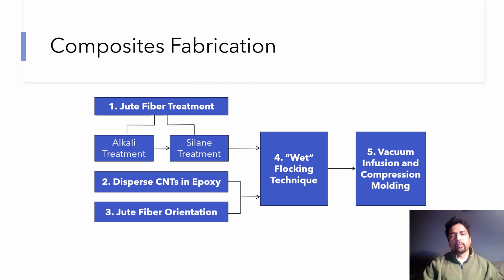The first thing is composites fabrication. In this study, we use jute fabric as the reinforcement and epoxy as the matrix. Jute, as you know, is hydrophilic in nature. It absorbs a lot of moisture. We do not want the jute fiber absorbing moisture under real-life applications when this composite is used. Hence, we wanted to make it hydrophobic. To make it hydrophobic, we treat these jute fibers in two steps: one is alkali treatment using NaOH solution, and the other is silane treatment. These two will eventually make the jute fiber hydrophobic. We will be showing you the results in the coming slides.